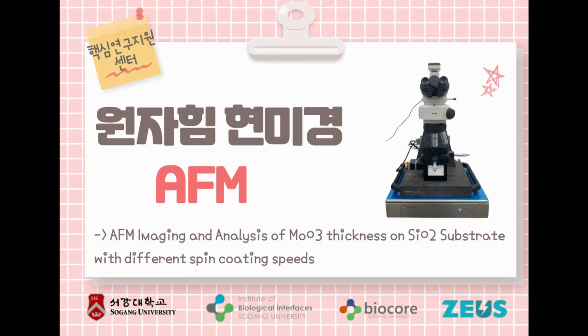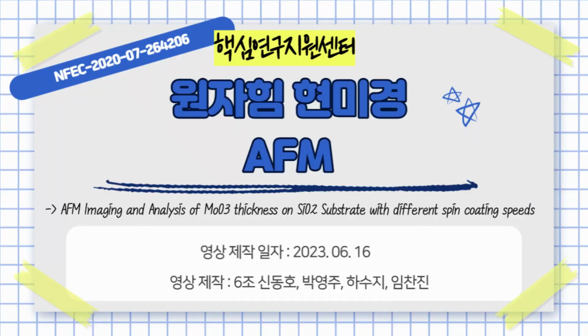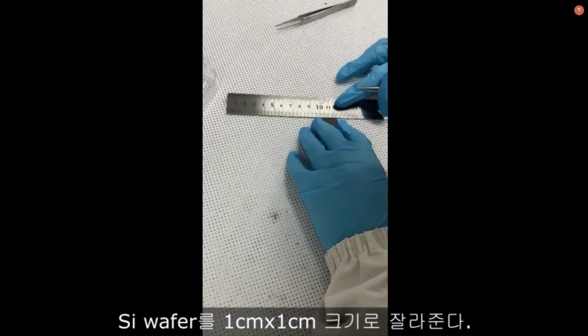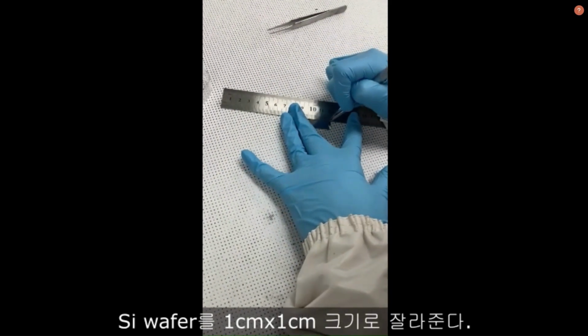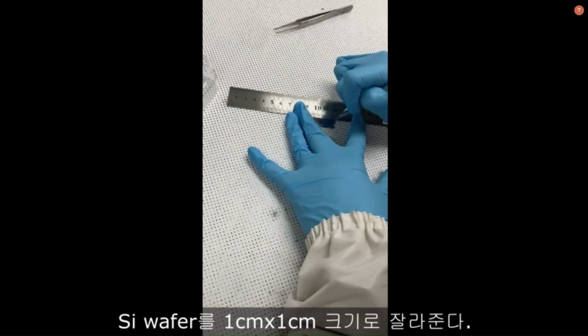AFM imaging and analysis of molybdenum trioxide thickness on SiO2 substrate with different spin coating speeds. Let's start with silicon wafer preparation. Cut the silicon wafer into the size of 1 cm by 1 cm.